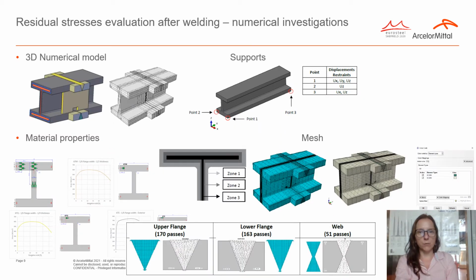The numerical simulation was made considering a multi-pass automatic welding process connecting 2 segments of the beam. The procedure was based on the input from the French Institut d'Études results, which performed the welding of the specimen for experimental testing and documented the procedure. The weld module interface AWI, an Abaqus plugin, was used to perform the welding simulations. It automatically creates all the analysis steps, energy transport boundary conditions, and builds the thermal model, followed by the automatic generation of the corresponding mechanical model for stress analysis.